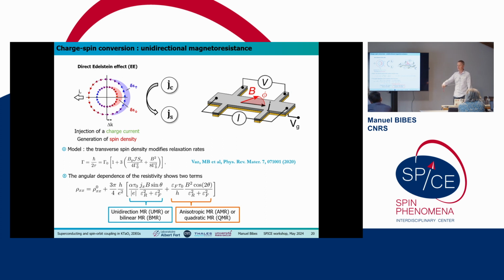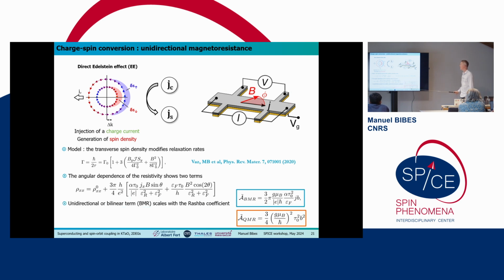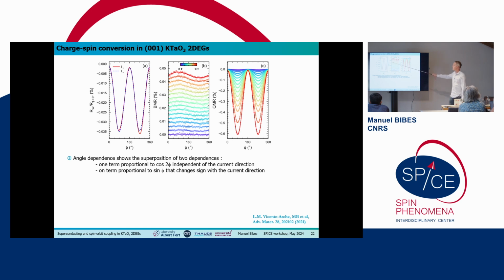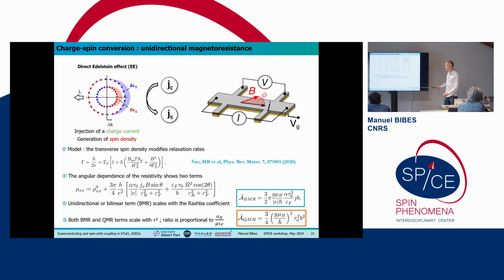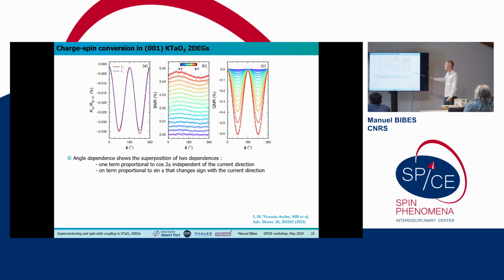So then we do angle-dependent transport measurements. We rotate the magnetic field in the plane with respect to the current, and we fit the data with this expression, and we extract the different parameters. So this is actually the data we get, and we measure for positive or negative currents. This term is not going to depend on the current sign. This one changes sign with the current sign. So then we can isolate the different terms by doing half sums and half differences.